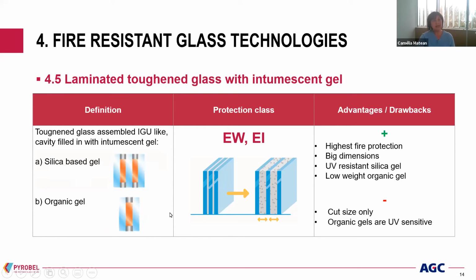The toughened glass is assembled in an insulated glazing unit and the cavity is filled with an intumescent gel. And we can have two types of gel: inorganic silica-based gel, and for this category we will have multi-chambered glass according to the rating we want to reach. Or we can have an organic, polymer-based gel, and then we will always have one chamber, thinner or thicker according to the rating. The action principle during the fire is the same, with the foaming gel.